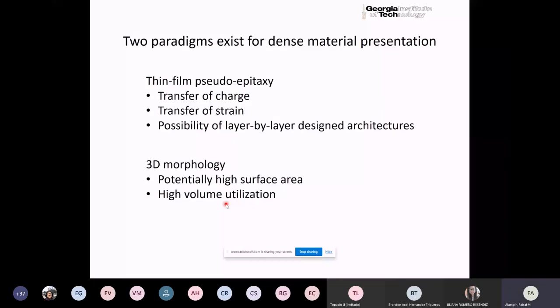And the 2D rendition of the catalyst allows us to do that. The second effect we could study is the strain. So the further away you get from the interface with the support, the lower is your potential strain, as long as you have epitaxial type of matching between the lattice of your catalyst and the lattice of your support.